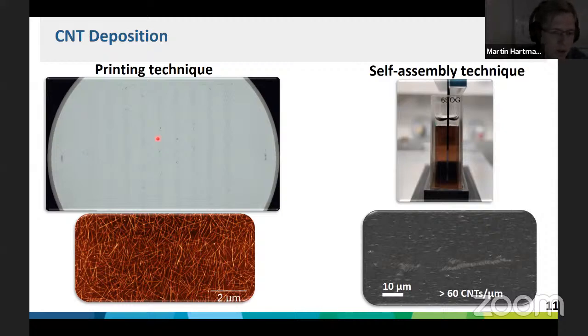We need here just a minor amount of dispersion. This is really almost nothing that we need. And we have the CNTs at the locations where we want them. Not for all applications, it's important to have a highly aligned layer of CNTs. And when we did the experiments that I will show you on the next slides, this process was the most reproducible process that we had. So we also went for this randomly aligned CNT layer for our high frequency CNT FETs, because we were not interested in having the fastest device, but we were interested in studying the geometry dependence. And therefore, we need a technique that yields reproducible CNT layers.